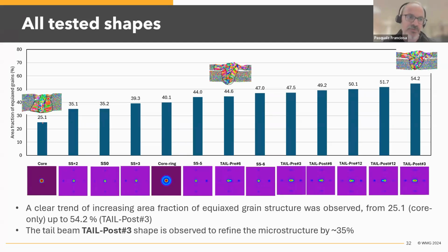You start from 25% area fraction of equiaxed grain, and you end up close to 55% equiaxed grain. This proves that by selecting the appropriate beam profile, there is clear evidence that you can tailor your microstructure. If you have 55% area fraction, it means there is more refinement and more grain boundaries within the weld, so the mechanical property of the weld is going to be improved. It's a stronger weld, because more grain boundaries means increased mechanical performance.